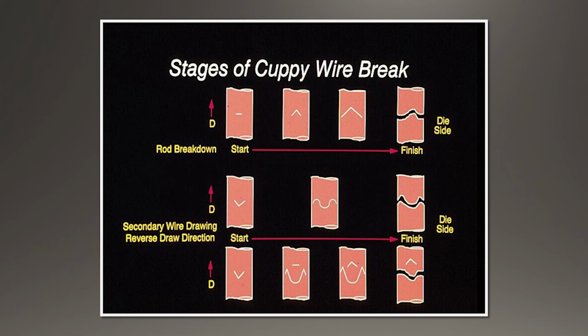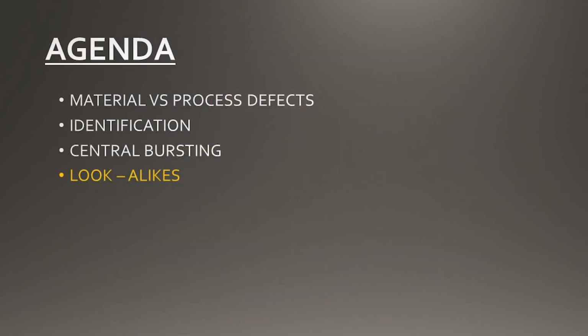Now, supposing once again that this is the wire going into the secondary machine and you start to draw it down. Now, supposing you got drawing problems in your secondary machine, then a crack may form. It's starting to form in a drawing direction. And in this particular case, you'll have cones pointing in opposite directions. And that's exactly like that picture that I showed just previously. Lookalikes.